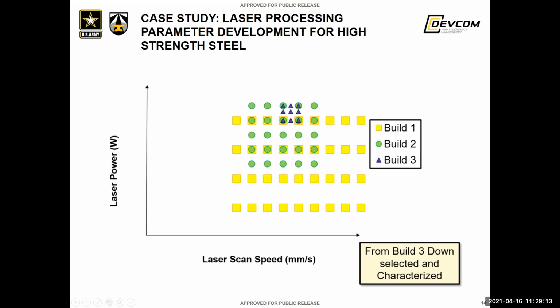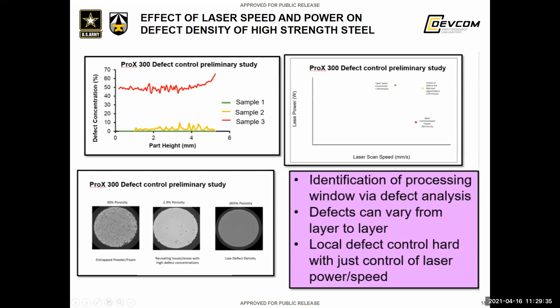So this is an example of what I did for AF96 on the Pro X300. Obviously, I had to hide the actual laser power and speed due to restrictions from my build site. And you can see that for this process, the actual processing parameters we can work with are very narrow. From this, we're also trying to identify the process window where we can have different defects, because maybe we want to include a soft area in our final part if it requires that. So we're looking at controlling the speed, power and hatch spacing to see where we can have a controllable defect. This is from our preliminary studies.